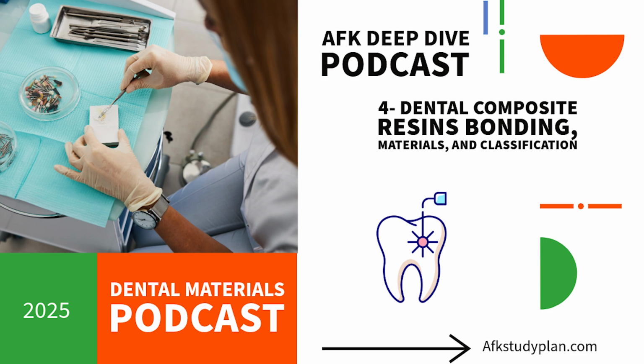Okay, makes sense. So how do dentists make the tooth surface have higher energy? Well, the sources point to having a clean surface, obviously, but also making it slightly rough on a micro level. And that's where the acid etch technique comes in. It's a real game changer. Acid etching sounds a bit aggressive. What's involved? It sounds intense, but it's very controlled. Usually it's phosphoric acid, maybe around 37% concentration. Its first job is to clean off something called the smear layer. That's just microscopic debris left from preparing the tooth. Like dust after drilling. Sort of, yeah. A mix of tooth dust and organic bits.